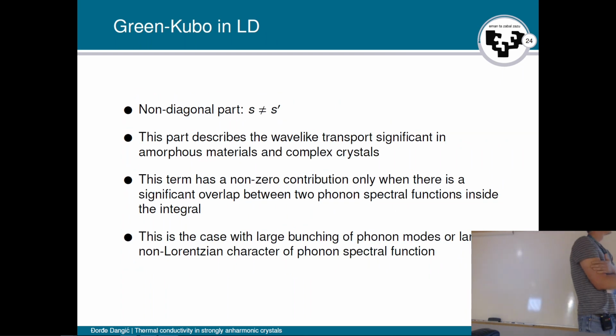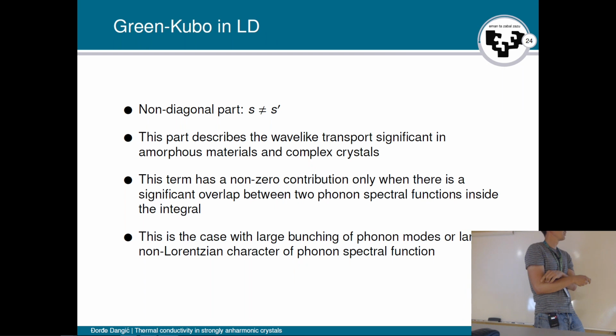The second part of the expression of the lattice thermal conductivity is the non-diagonal part, so the part where phonon branches are not equal. And this part has for a long time been neglected in the calculations. But recently it has been shown that this part describes a wave-like transport, which is significant in amorphous materials and complex crystals. And this is something that you saw in one of the talks from yesterday. So in the case of amorphous materials, this type of transport is important.